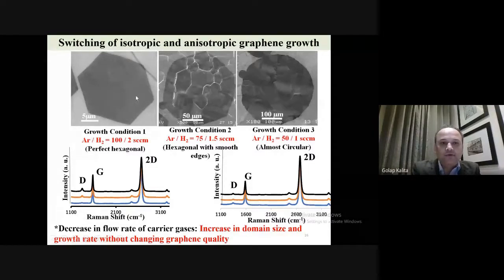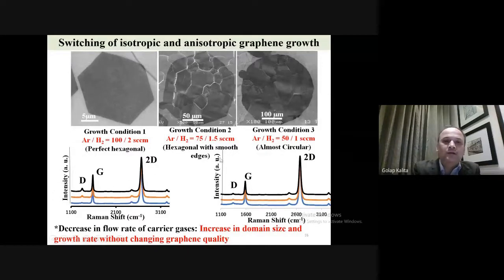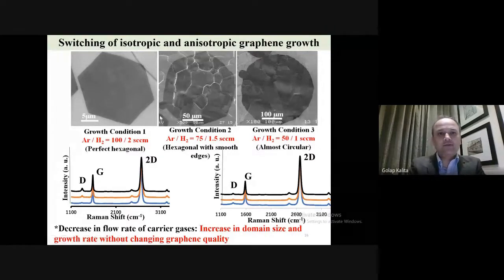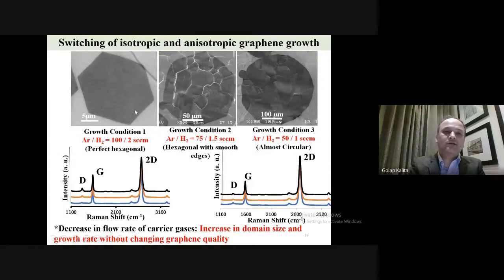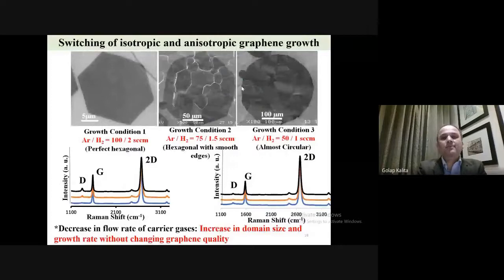In both cases, if we see the Raman peak of the crystals, it's a monolayer crystal, and good quality for both cases. So once again, in anisotropic we have small hexagonal crystals. This is just 5 micron scale, but in the same growth time, we can have a very large graphene crystal on the copper substrate. Okay, so this was what I discussed, some interesting aspects of graphene growth by CVD.